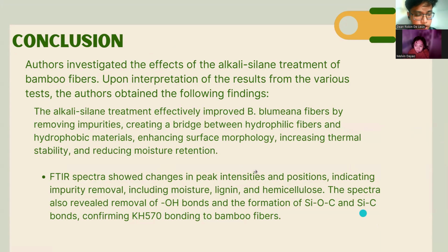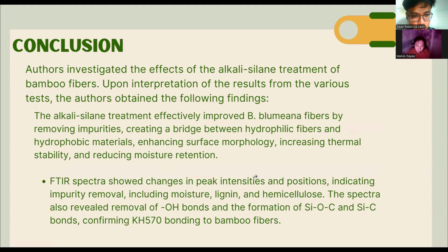To conclude the study, the authors investigated the effects of the alkali-silane treatment of bamboo fibers, and upon interpretation of the results from the tests, the authors obtained the following findings. The alkali-silane treatment effectively improved the Bambusa blumeana fibers by removing impurities, creating a bridge between hydrophilic fibers and hydrophobic materials, enhancing surface morphology, increasing thermal stability, and reducing moisture retention.